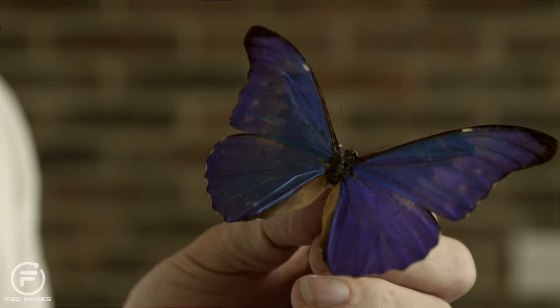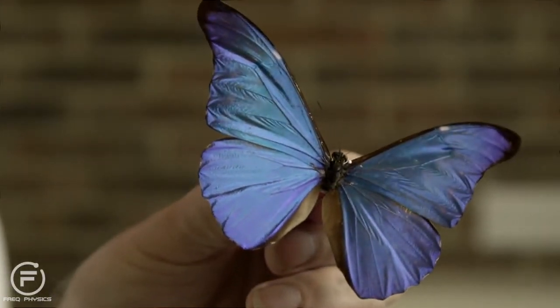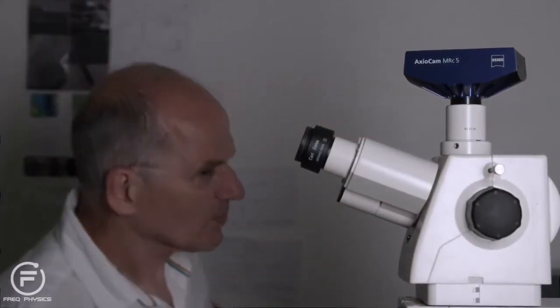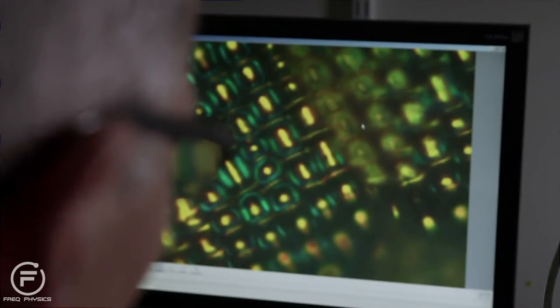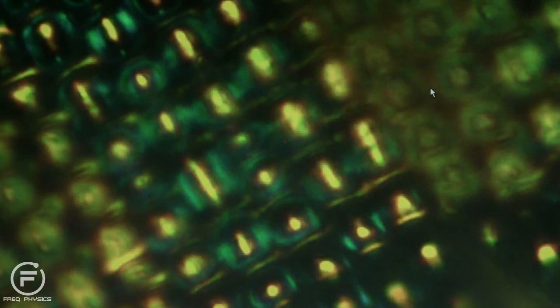We just need to know. If you take a butterfly and you look at its wing scales, it's got very tiny wing scales, about 50 microns by 100. We found that within the wing scale, which is more or less fingernail material, the butterfly had created tiny sculpted structures — nanostructures — which gave interference, which gave diffraction. Those effects combined can give you a variety of different vivid colour effects.